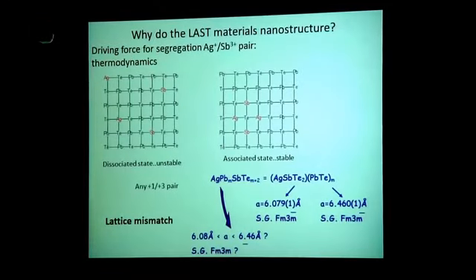So why does it do that? One reason is the difference in lattice parameters: you have two different phases, essentially mixing 2 different phases with a large difference in lattice parameters. That could be a driving force for phase separation.